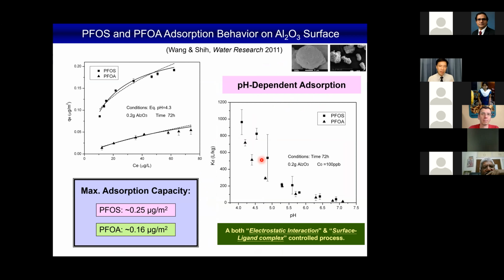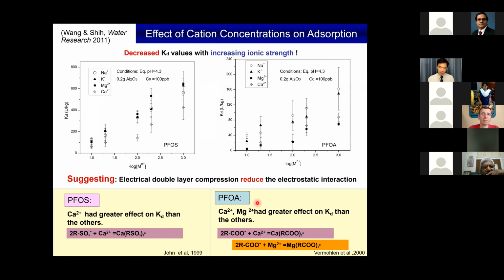So we want to understand the behavior of this type of pollutant in the natural environment. We started by looking at the adsorption behavior, and we find that at relatively lower pH you have much larger adsorption capability for this kind of compound. PFOS is still the one that adsorbs more, PFOA slightly less. So you should be very, very careful when you are doing, say, sludge treatments, or even putting it in a landfill. You will have a chance of having them in a lower pH range, and then there is more chance for the compounds to be adsorbed on the soil.